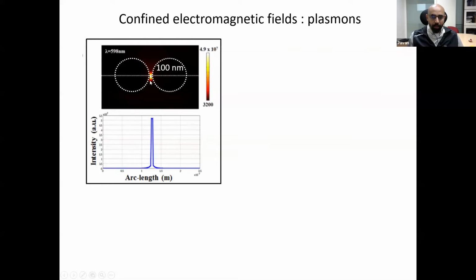If you have, let's say, a molecule which has a very interesting Raman scattering signal, this molecule can be freely floating in this gap, which means that it is only now subject to an electromagnetic field. Otherwise, the molecule can also adsorb onto this particular nanoparticle, which means that the surface selection rules govern the modes of vibrations of that particular molecule, and it can give rise to some wonderful and very interesting effects.